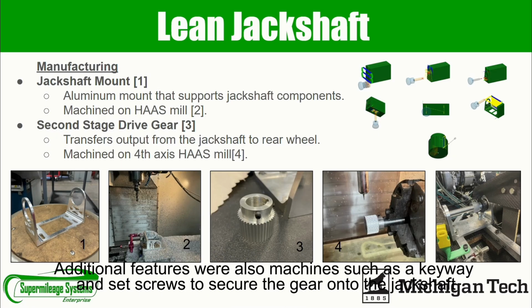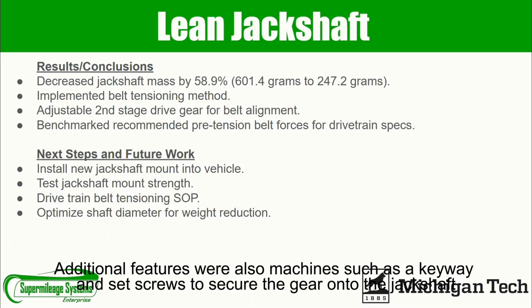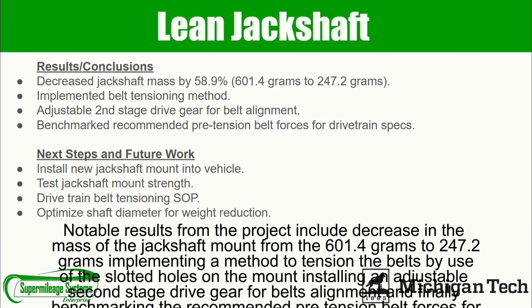Additional features were also machined, such as a keyway and set screws to secure the gear onto the jackshaft. Notable results from the project include decreasing the mass of the jackshaft mount from 601.4 grams to 247.2 grams, implementing a method to tension the belts by use of the slotted holes on the mount, installing an adjustable second stage drive gear for belt alignment, and finally benchmarking the recommended pre-tension belt forces for our drivetrain specs.